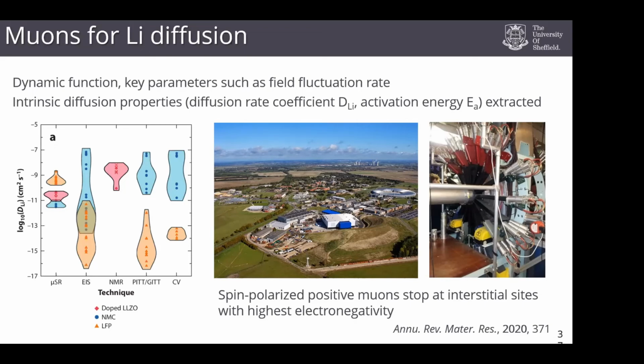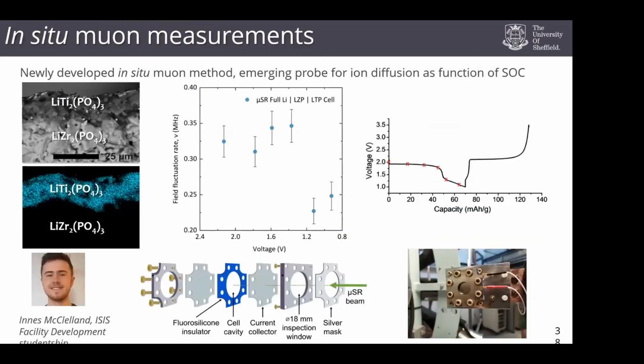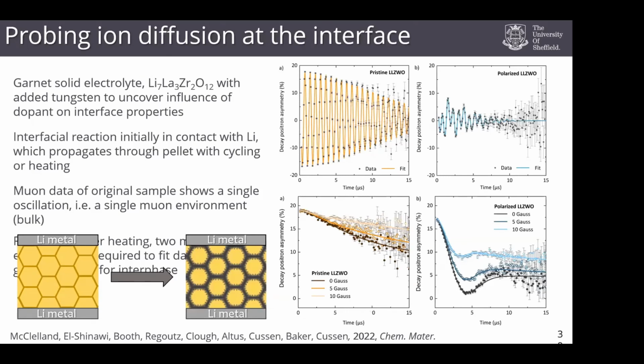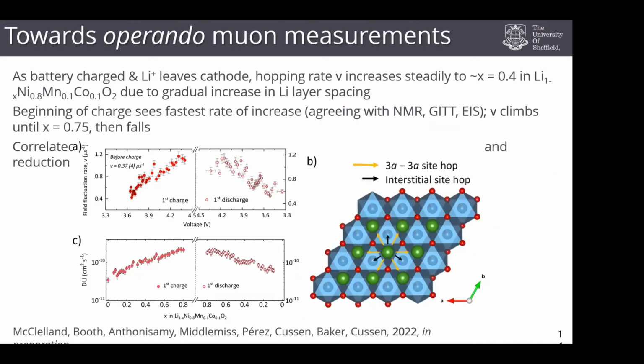And what we've been doing increasingly in Sheffield, I'm not going to go through this, is developing new methods at the ISIS neutron and muon facility for not just studying the diffusion properties of the powder material. We've actually built battery cells that you can put on that muon beamline, and you can start to interrogate what happens in solid state batteries when lithium metal is reacting with your electrolyte, forming additional phases. You can also look at what happens to lithium diffusion coefficients as you charge and discharge a battery. That's just what this graph here is showing you.